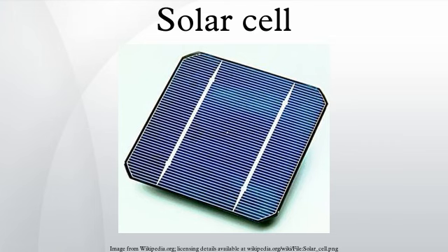Typically a ruthenium metal organic dye is used as a monolayer of light-absorbing material. The dye-sensitized solar cell depends on a mesoporous layer of nanoparticulate titanium dioxide to greatly amplify the surface area, 200 to 300 m2 per gram of TiO2, as compared to approximately 10 m2 per gram of flat single crystal. The photogenerated electrons from the light-absorbing dye are passed on to the N-type TiO2 and the holes are absorbed by an electrolyte on the other side of the dye. The circuit is completed by a redox couple in the electrolyte, which can be liquid or solid.